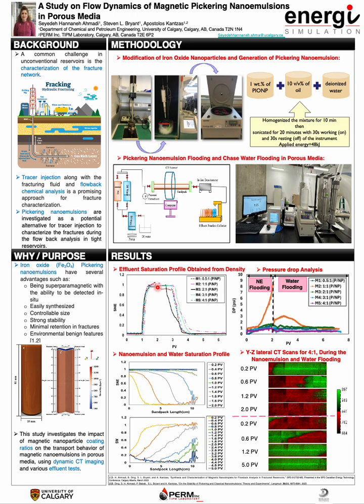As you can see in this figure, nanoemulsion production persisted during chase water flooding up to 2.2 pore volumes for M1, 3.2 for M2, 2.7 for M3, 3.3 for M4, and 3 for M5, as indicated by the saturation measurement during the chase water flooding, aligning closely with the nanoemulsion saturation baseline. This consistent saturation suggests stable production of the nanoemulsion.